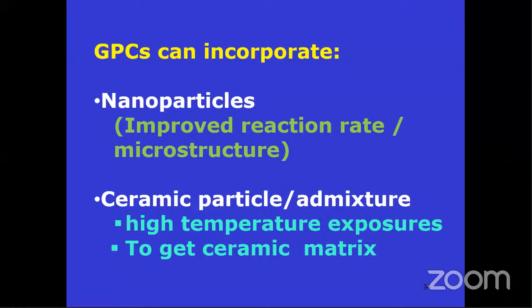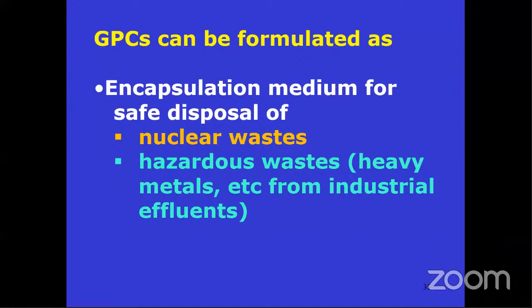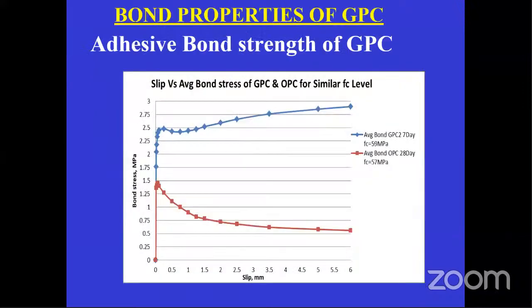Otherwise, geopolymer is not high temperature resistant in general, what you do in India. It is always maybe 100 degrees, 200 degrees. More than 300, it will be as bad as ordinary concrete or as good as ordinary concrete. Okay, and encapsulation studies were also made, nuclear waste utilization and disposal. This also, slightly initial work, I have done in SERC and in SRM with the physics department, biotechnology department and nuclear division there. We did that work. But this is what I wanted. With this, I will close my work on geopolymer test data.